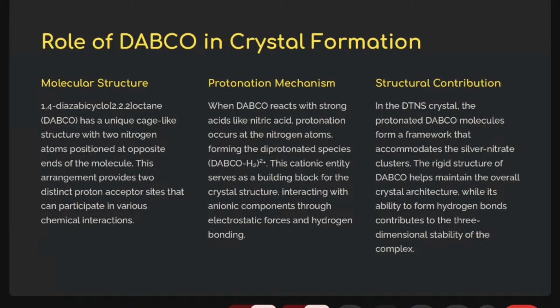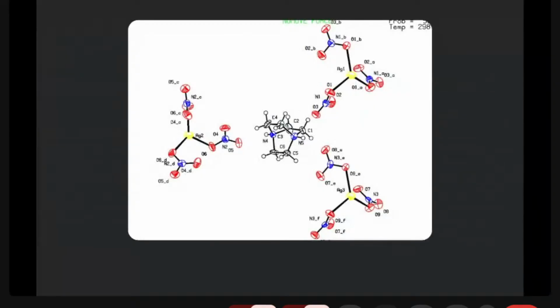Now, the role of the DABCO in the crystal formation. As we know, the DABCO's critical feature is the protonation mechanism. The protonated DABCO molecules stabilize the entire structure, accommodating the silver nitrate cluster in a spatially ordered fashion. It rigidly maintains the crystal structure, ensuring that the lattice does not collapse or deform. At the same time, nitrogen centers continue to participate in hydrogen bonding, which enhances the three-dimensional integrity of the crystal. These intermolecular interactions, hydrogen bonding, create a network that is crucial for the crystal's mechanical strength and thermal stability.